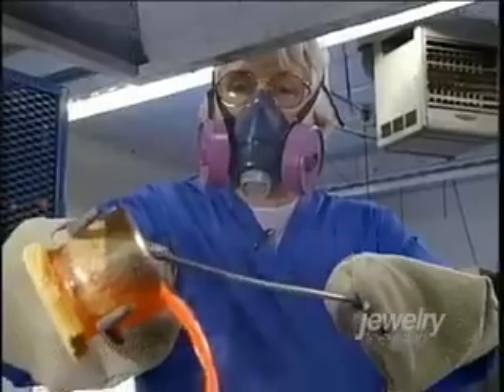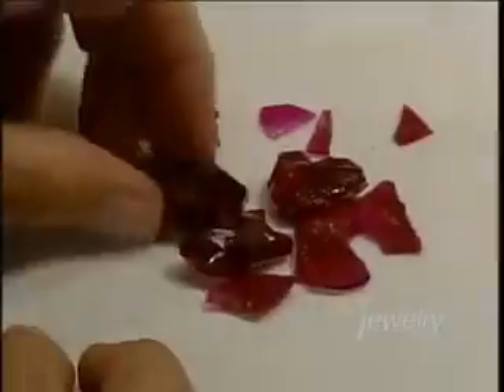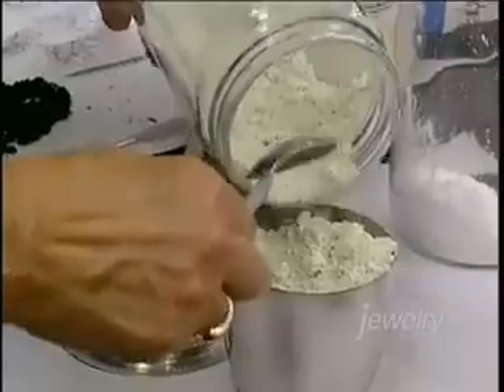And that melt falls as droplets on a cylinder and it envelopes the cylinder. And the cylinder is lowered as the boule grows. Within hours, a synthetic ruby or sapphire can be grown using flame fusion. But there are disadvantages. Those boules are under stress because they crystallize pretty fast, so typically they break in half lengthwise. So the maximum size of the gem that you're going to get is given by half the size of the boule.